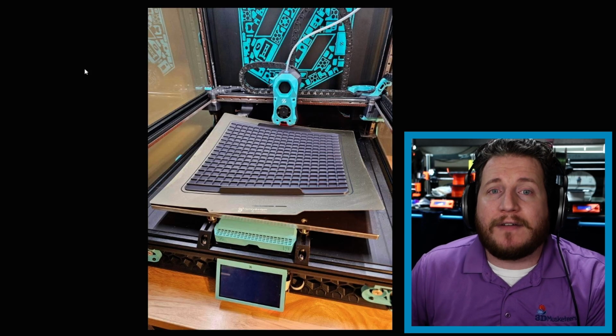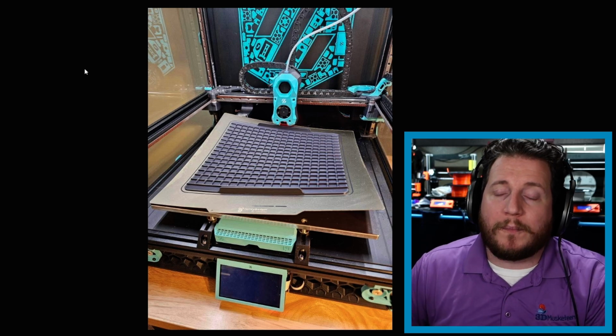A great way to deal with this is to not only actively heat the chamber, but when the print is done, actively cool it down by slowly lowering the temperature rather than just shutting off the actual heaters themselves. You can control the ramp down of temperature inside of that chamber. With higher temp materials, you can crank those temperatures in that chamber and the part will love it. But if you thermally shock it, it will have a tendency to shrink and warp up, as we see.